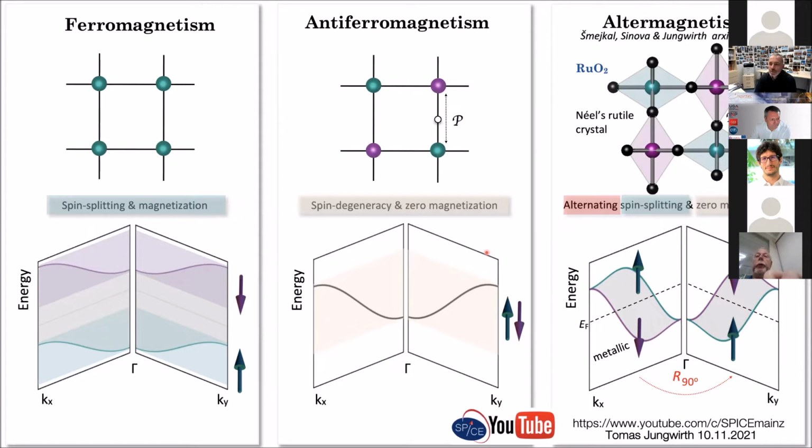These are non-compensated, zero magnetization spin systems, but in this case the symmetry of the system is governed by non-relativistic physics and shows a spin splitting that is related by rotational symmetries in the system that have a lot of the aspects of ferromagnetism, showing spin splittings that are very, very large, dominated by the electric crystal field, and that can give rise to GMR effects as well, and TMR effects, which are not believed to be the case, for example, in these run-of-the-mill PT antiferromagnets that are spin degenerate.